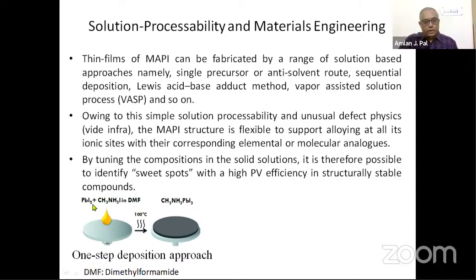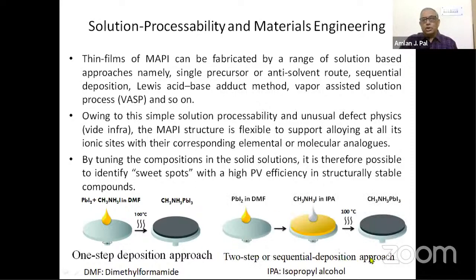So what we do generally in the lab is, you just mix lead iodide and methyl ammonium iodide in DMF. DMF is dimethyl formamide. You mix it, then spin it, anneal it, and you get a methyl ammonium lead iodide film. A little different approach is the two-step or sequential deposition approach, where you first deposit a lead iodide in DMF thin film through the spinning method, then methyl ammonium iodide in IPA. IPA is basically isopropyl alcohol, which you use these days in sanitizer. And then you just spin it, you again anneal it, and you get the methyl ammonium lead iodide. So it's a simple lab-based approach, and that is the way it is working.